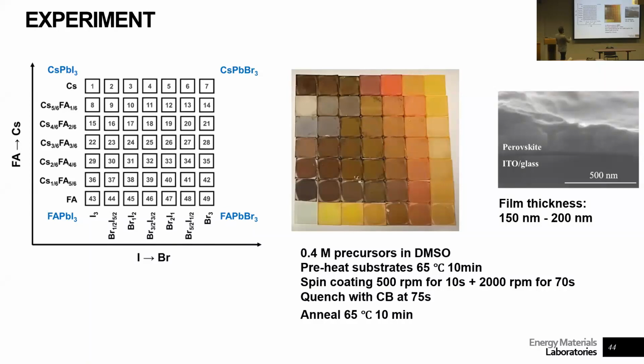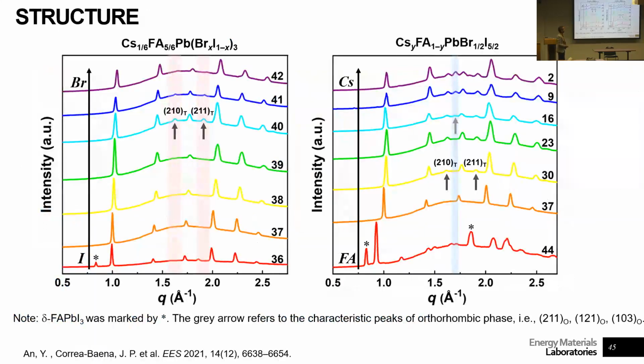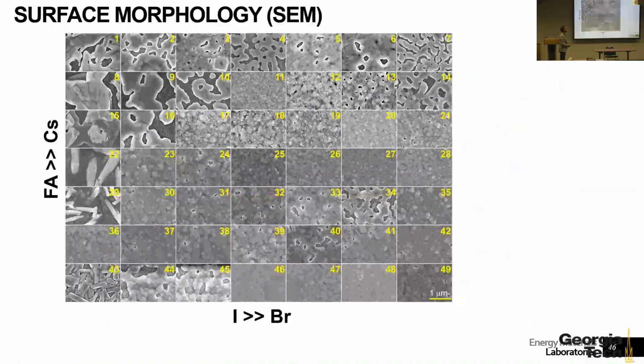And we can do this experimentally, basically from solution is easier than from vapor, but at least to screen is a very good way for us to work on this and identify materials. So in this study, we did actually 49 compositions, and we measure all the structure and all the property features. And so here's GIWAXS, X-ray scattering that we did on all those films. We did 49 of those at different angles. So we had hundreds and hundreds of data points. It took about a year for us to actually go through all that data.